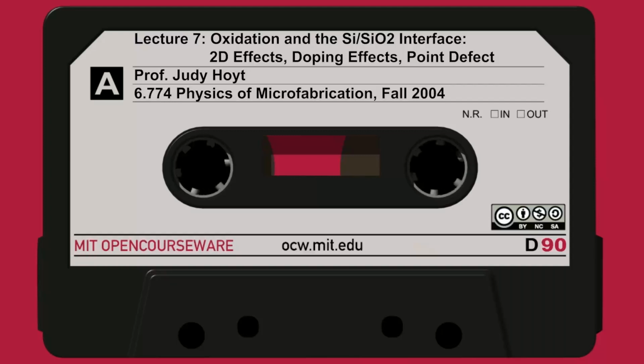What people typically do is grow an oxide at 800 or 900 for an hour. The last step of the program is to let the wafer sit at 800 or 900 in the tube with no oxygen flowing, just argon or nitrogen. And that last half-hour anneal is the QF anneal.